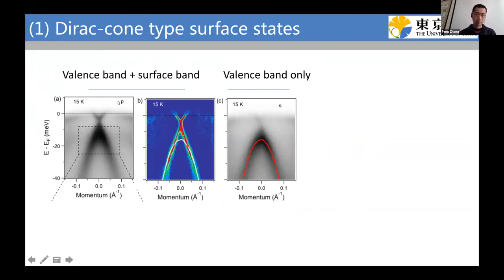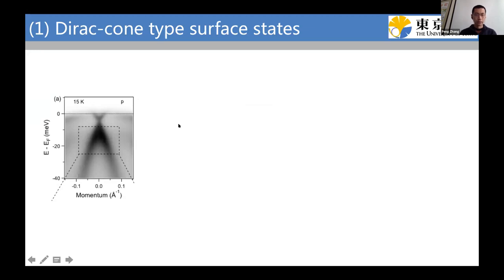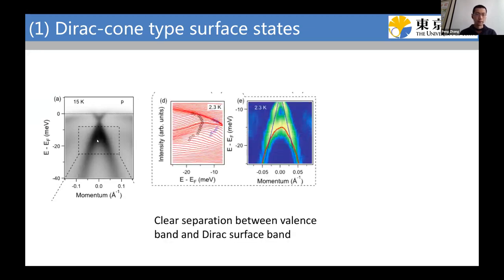with p-polarized light, which is sensitive to p orbital bands. If we change the photon polarization to S, which is sensitive to the dxz orbitals, we only see a parabolic band. So the band structure should be like this. We have a parabolic valence band, and on top of this band, there is a cone structure. We can directly resolve this feature from raw data.